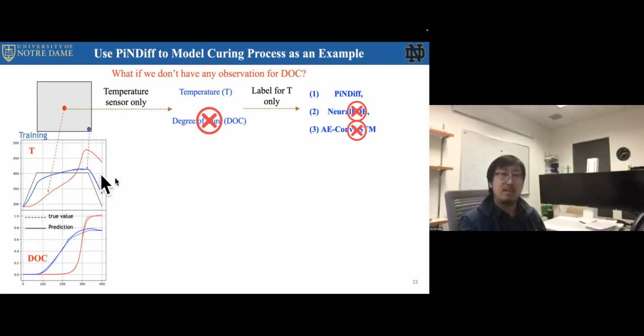So this is the result. For the training, we are going to take the temperature and train the models. After training, you can test your models on different locations, and you can get the temperature predictions, but also the degree of cure. Those are the degree of cure at the center and the corner. So it agrees with the ground truth pretty well.